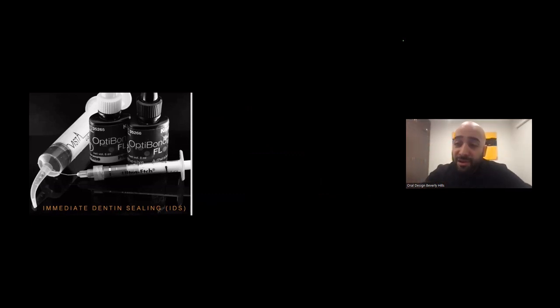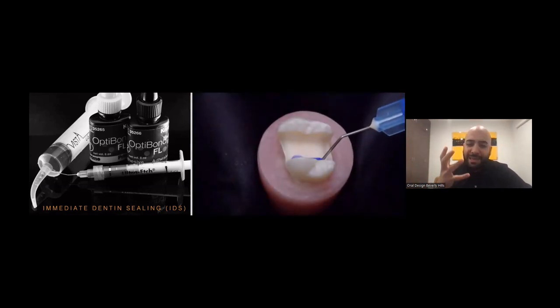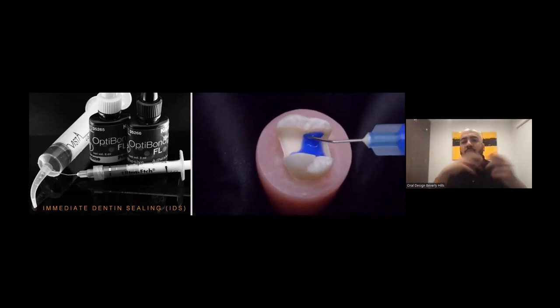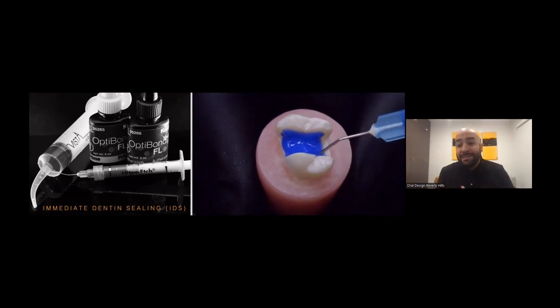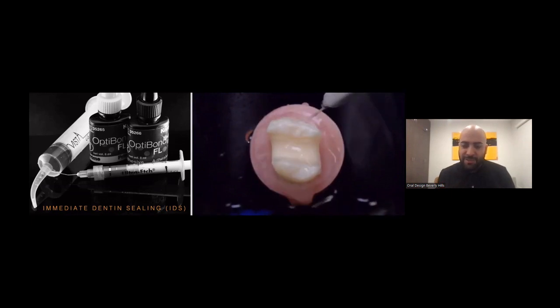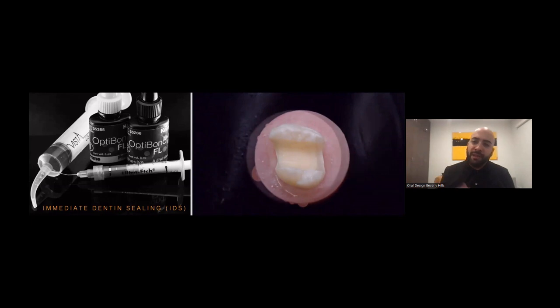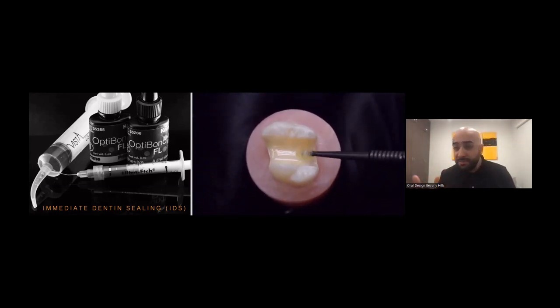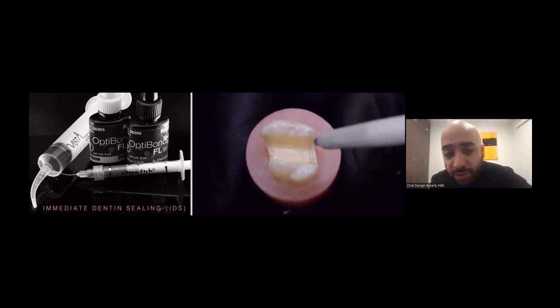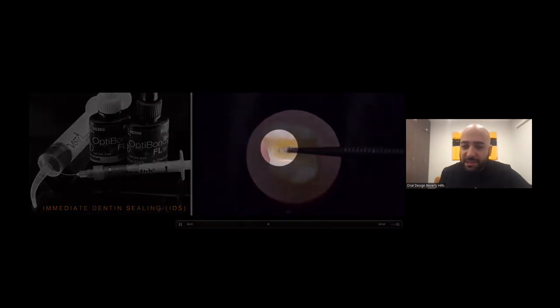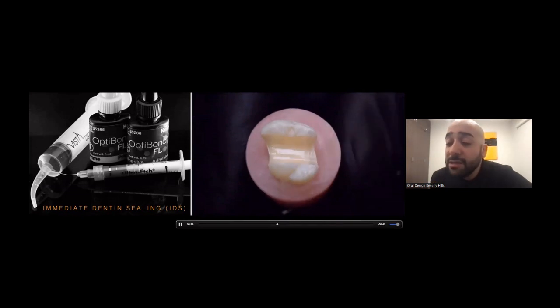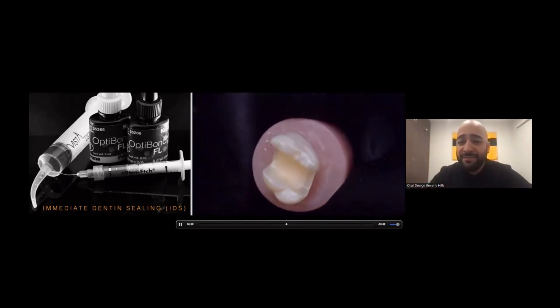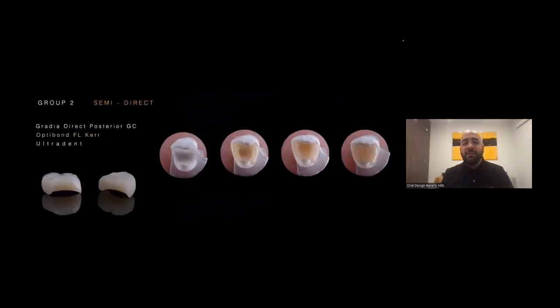Now, our second and third groups are what we're comparing these restorations with, and that's our semi-direct and our indirect restoration. Now, for both of these groups, we run all the samples through what we call immediate dentin sealing, which is one of the most wonderful findings and givings of resin. Immediate dentin sealing means right after we prepare these teeth, before we run them through temporization or bonding of our semi-direct or indirect restorations, we follow our bonding protocols here with Optibond FL, and we bond and seal only the dentin layer inside these restorations. We're going to talk a little bit more about this in the end and explore the advantages of immediate dentin sealing. Once all the samples for the second and third group go through IDS, then we start applying it.